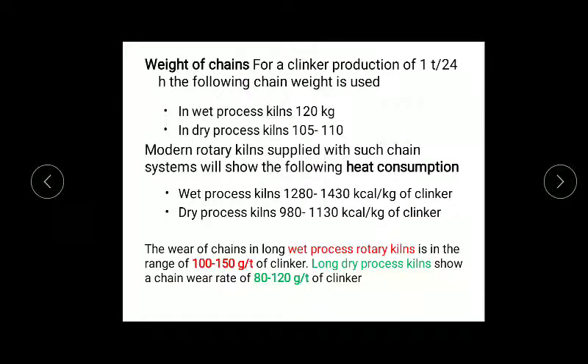Weight of the chain. For a clinker production of 1 ton per 24 hours, the following chain weight is used. In wet process, it should be 120 kg. In dry process, it should be 105 to 110 kg. Modern rotary kiln supplied with such chain system will show the following heat consumption. How much is the heat consumption if you are using chain system? For wet process, it would be around 1280 to 1430 kilocalories per kg of clinker. For dry process, it would be 980 to 1130 kilocalories per kg of clinker.